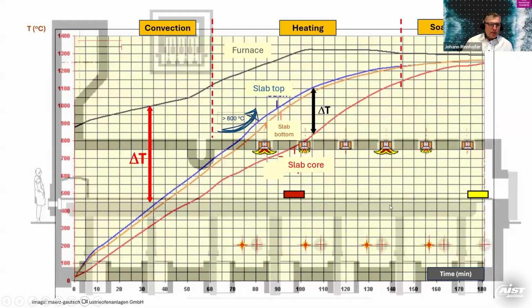When we look into the heating curve or the temperature curve of these furnaces, they usually look like this. So we start the heating process with cold steel, or it can also be preheated, but usually cold. And then we have a furnace temperature in the range of, say, 700 to 900 degrees usually in these furnaces. And you have a very high temperature difference.